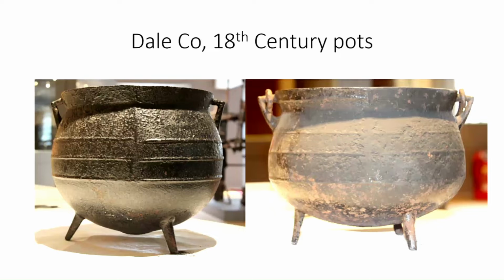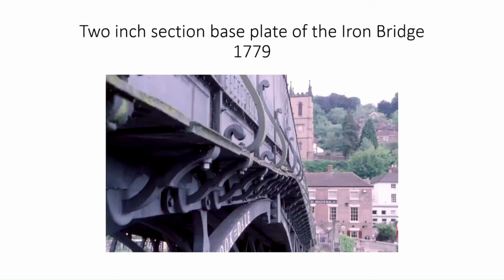when he first used coke in the blast furnace, because the one thing that coke iron could do better than charcoal iron was make a thin casting. It naturally produced a high phosphorus and a high silicon. You had to choose the ore to get the right high phosphorus. But basically a 2-inch casting, in old money, by the way, is the base plate of the iron bridge,